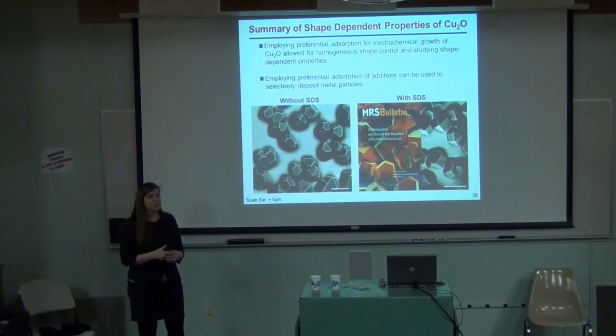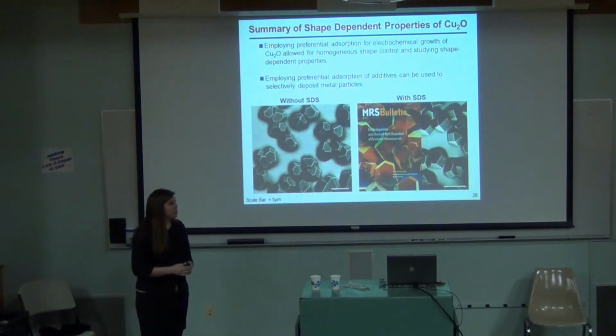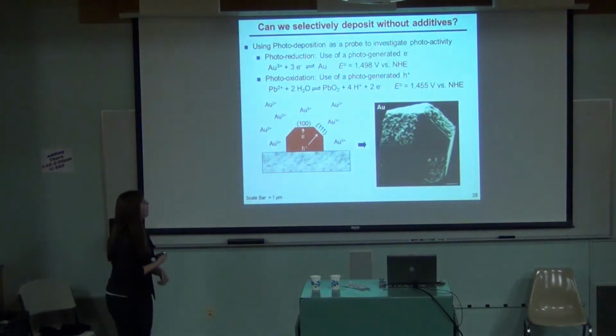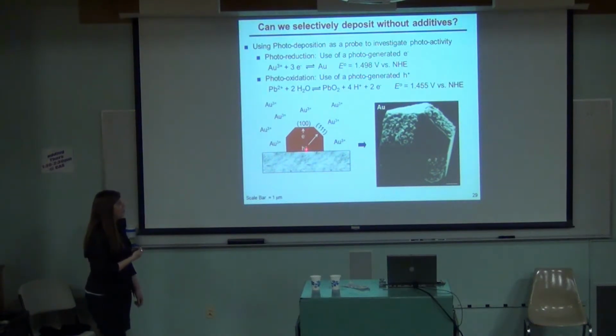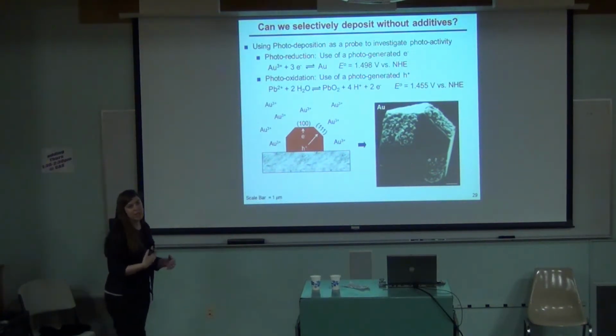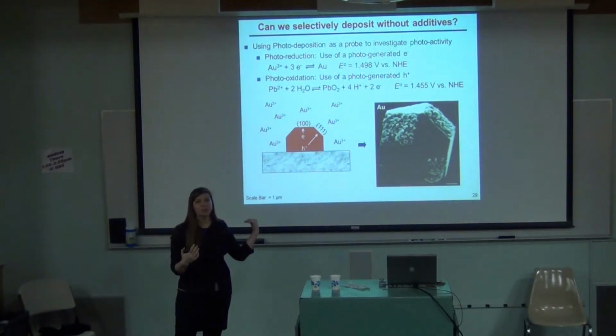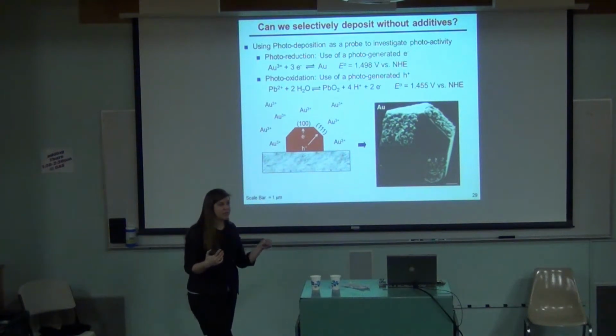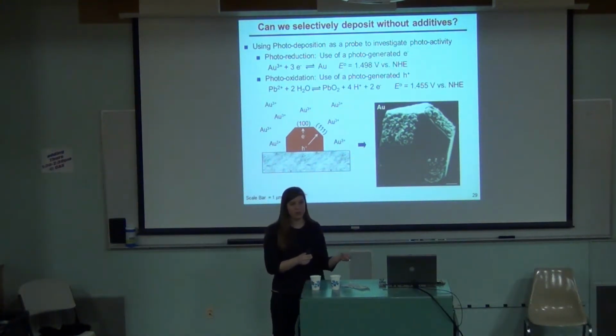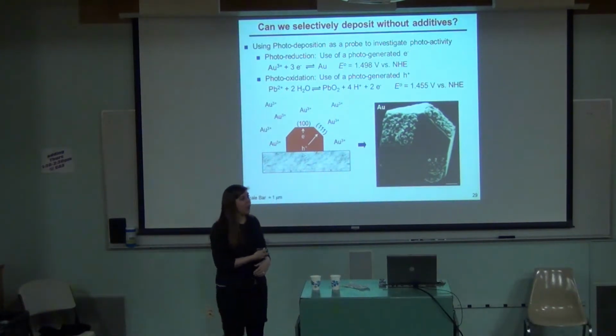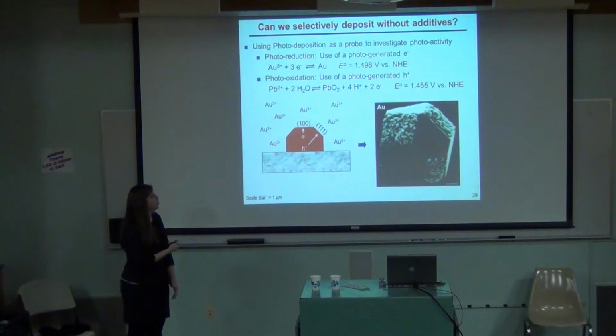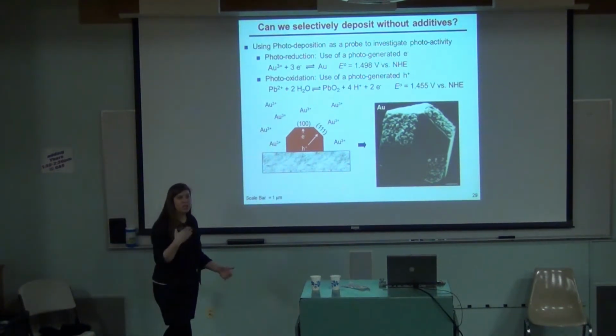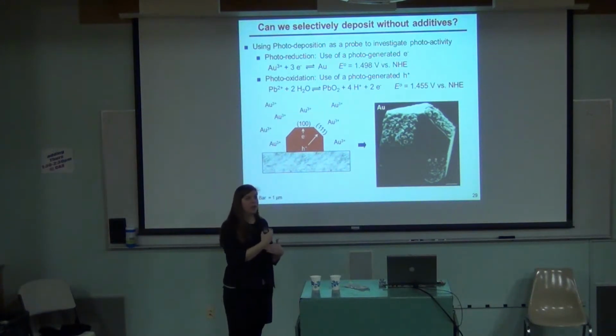So some of the students may know what Material Research Society is. They always have the fall meeting in Boston, and so we got to publish in this journal, which was great. The other thing I did with this is I wanted to see if you could photo deposit selectively. And so first, when I showed you the previous one, we were electrodepositing gold. So we were taking gold cations in solution, reducing it to gold metal on the surface. This is the same process, except instead of applying a potential to reduce it, we wanted the light to do that. We wanted the sun to do the reducing. And we thought that it would selectively reduce only on the surfaces that were creating electrons, because you need an electron to be able to go from gold 3+ to gold metal.